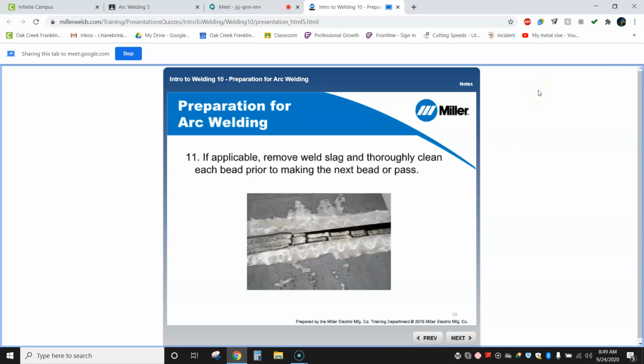If applicable, remove weld slag and thoroughly clean each bead prior to making the next bead or pass. This is very, very true on multi-pass welds. You can see here we've got a root, and we got 1, 2, 3, 4, 5, 6, 7, 8, 9, 10, 11. So by the time they get to the top here, they've got 11 or so, maybe even 13 passes to fill this gap. If they're not cleaning that slag out 100% and making that thing shine before each pass, you're going to get what are called slag inclusions, and those are prone to cracking, to breaking, to porosity. And if this one gets UT'd, where they do an ultrasonic test on it, they'll see that slag inclusion, and you'll have to sit there and grind it all out to get rid of it and re-weld everything.